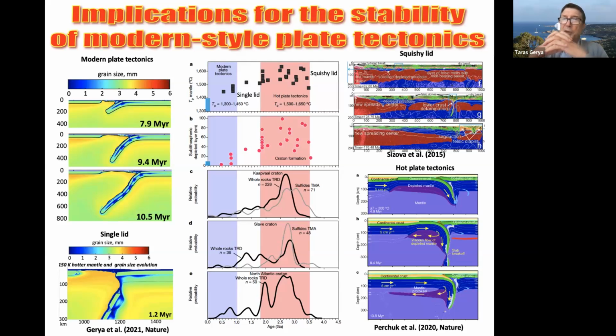Exactly. Yes. Thank you very much for this question. The first people who suggested the prevalence of slab breakoff at hot mantle potential temperature were Jeroen van Hunen and Arie van den Berg. They published a seminal paper in 2008 in Lithos, where they showed that this tendency arises in modern style subduction models with mantle temperature increase. The only difference with this study is that typically this breakoff tendency becomes prevalent at much hotter mantle temperature. So we need to increase mantle temperature by 200, 250 or 300 degrees, essentially somewhere corresponding to Archean time, to have this highly intermittent subduction.